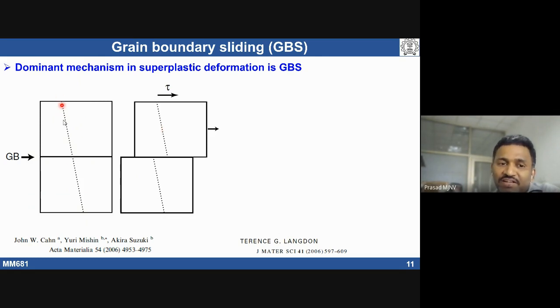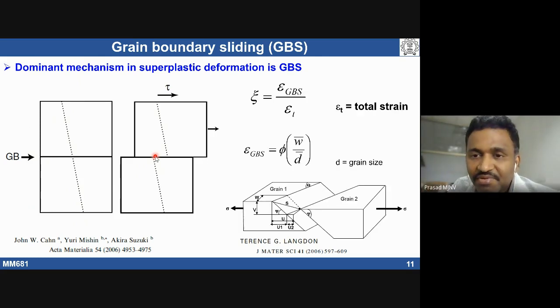Initially I have a marker like this. If the material is deformed and there is grain boundary sliding, the marker is going to shift by a certain width. The sliding with respect to the original grain size is taken as the grain boundary sliding strain. If we take a simple three-dimensional view of the grain structure, the contribution of grain boundary sliding strain to the total strain is represented as xi.